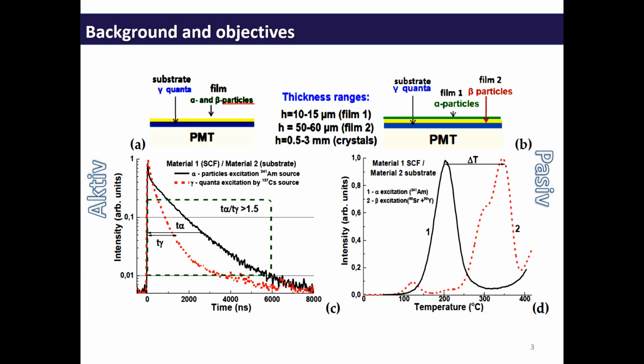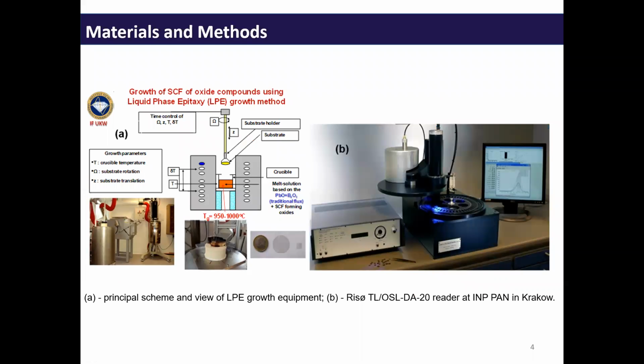Nowadays, we consider a new possibility for simultaneous registration of the different components of mixed ionizing fluxes using differences between the TL glow curves coming from the film and substrate parts of a composite detector. Thermoluminescent detectors were grown using the LPE method from the melt solution based on the PbO flux.